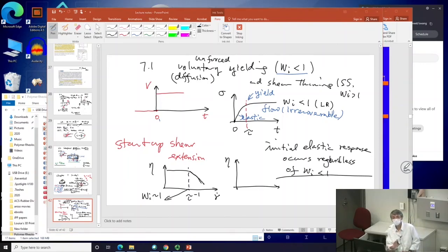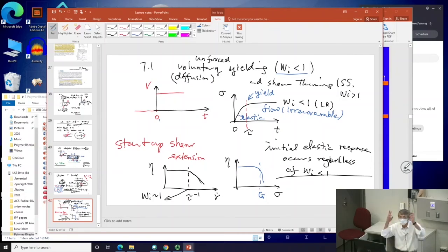I know it's unfamiliar for you. Like Alex, you took rheology before. Viscosity commonly as a function of rate gives you shear thinning. There's another notion much more powerful, especially for dealing with polydispersed samples, for example. It is viscosity plotted, instead of against shear rate, against shear stress. Okay? And when you do that, it plunges around a level which is the plateau modulus. In other words, with respect to stress, the thinning is much stronger.